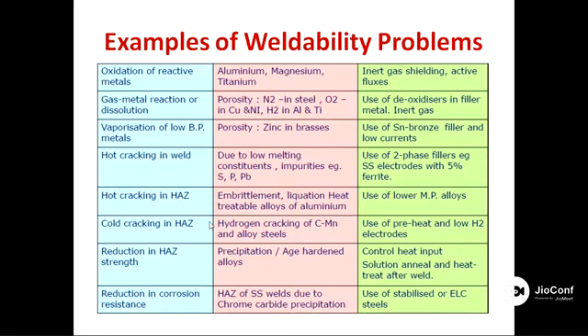Then hot cracking in the heat affected zone. Again, embrittlement issues, liquation in the heat affected zone of aluminum alloys, hot cracks, and use of low melting point alloys. I also included some slides on welding of aluminum, because it is the most used material in your automobile application. But for automobile application, we'll try to use a material with lower melting point alloys near to the eutectic point, or aluminum silicon or aluminum magnesium. Aluminum 5% silicon, aluminum 5% magnesium. Why? I'll explain when the slide comes in subsequent slides.